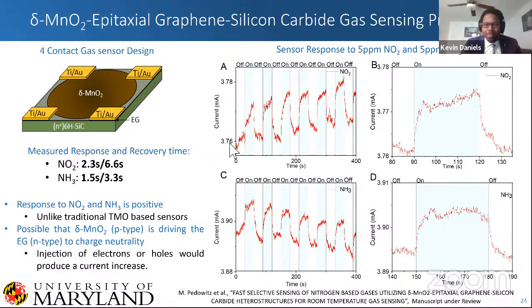And so we cycled gases on, our NO2 and our NH3, and we cycled it on and off. And we're able to see this very, very fast response and recovery time to these gases. Now, the issue here is the responses are both positive, which you would not expect, since oxidizing and reducing gases would actually have different and opposite effects in response to landing on a material.